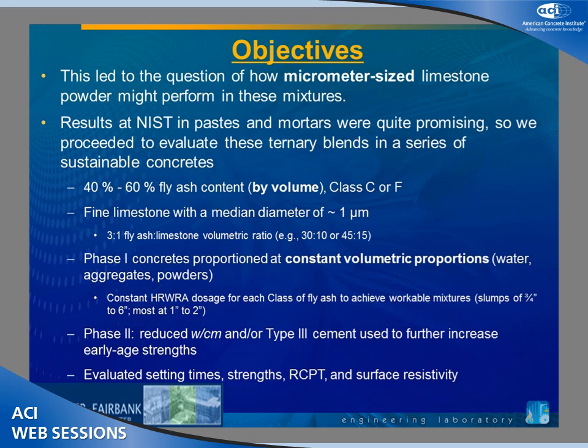We kept a constant high-range water reducer dosage for each class of fly ash. So our control system with ordinary Portland cement had 1 dosage. We found with the Class C or the Class F, we were able to reduce that dosage by different amounts, and then we maintained that for any of the mixtures that were made with that particular fly ash. We were very successful, as you'll see, at reducing the setting times back to the controlled concretes.